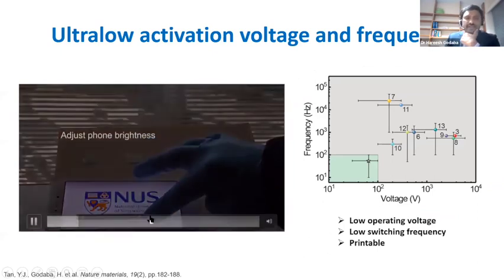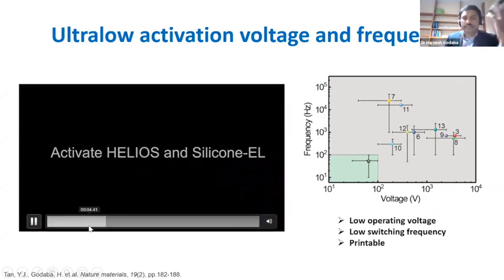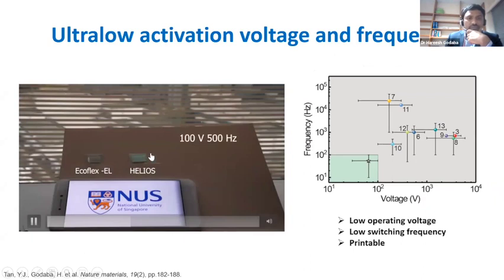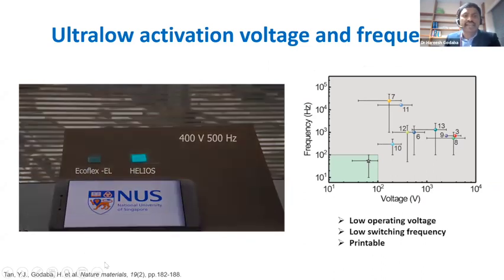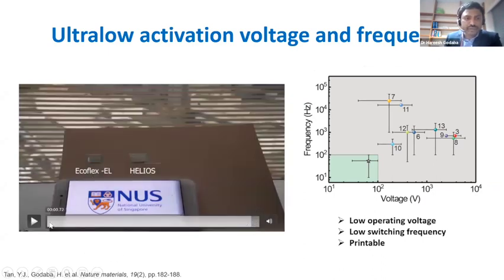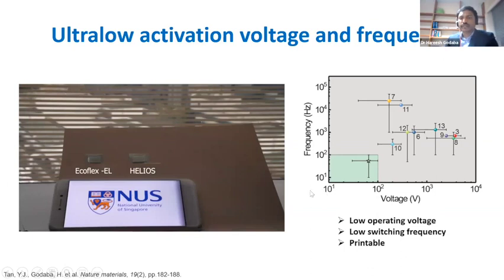So this is basically a normal mobile phone in daylight. And here on the right side we have the Helios device which we've developed, and on the left you have a control group, which is another EL device with a different dielectric that was used before in literature. And you can see that the Helios material is significantly brighter compared to the control group. And we actually see that the voltage and the switching frequency are quite low compared to most of the other works in this domain.